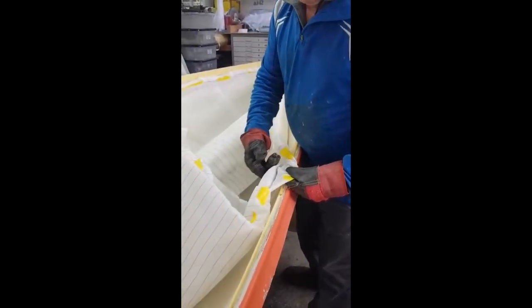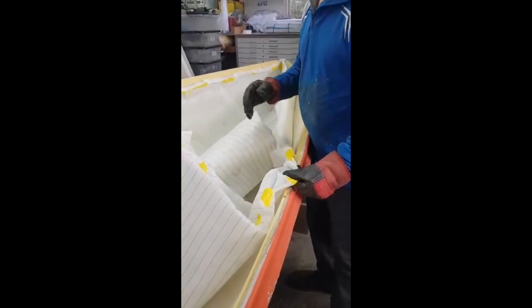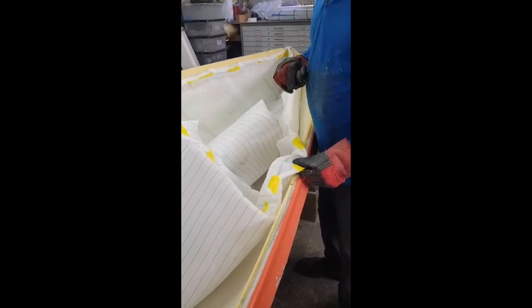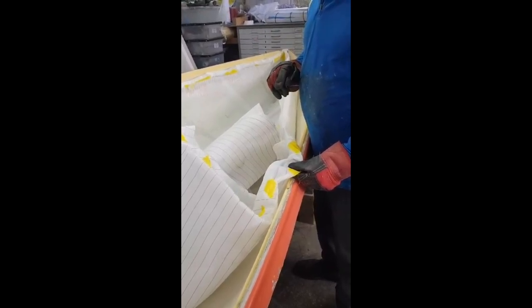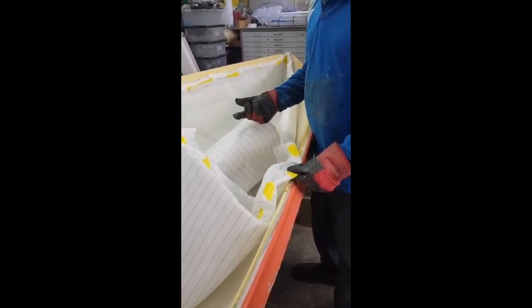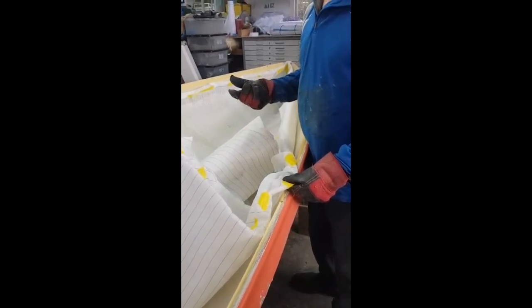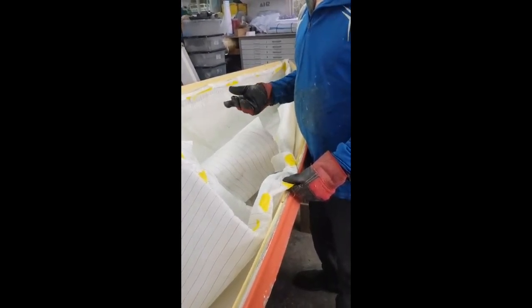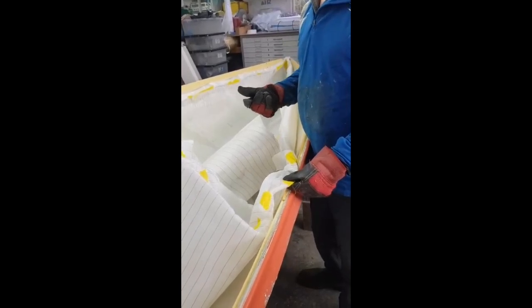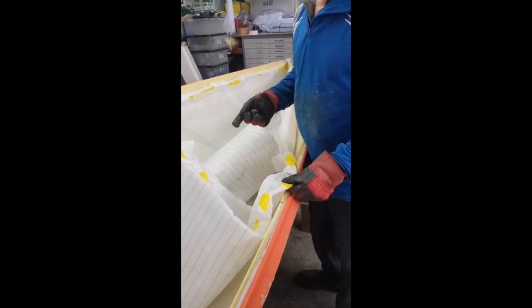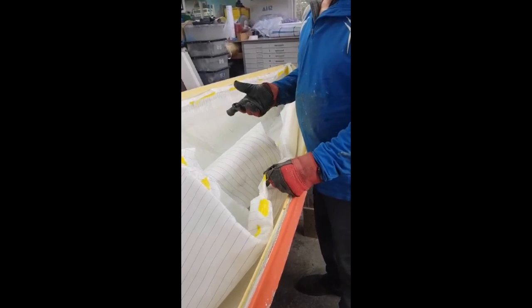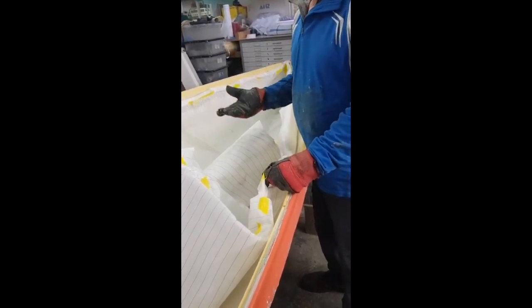Then this breather film also acts as an airway to make sure that we've got even vacuum all over the mould whilst it's been vacuumed down. So when we were doing the heat process, we kept the vacuum on full time to make sure there was no distortion from the mould. I dare say that's never happened before in a Javelin build. As this would have never happened either, because it's an epoxy build.